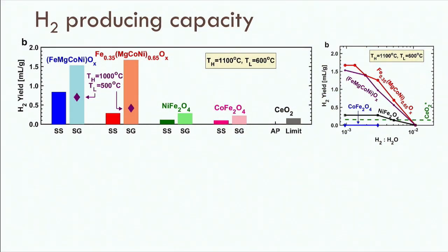In the interest of time, I'll keep it short. This is at 1100 degrees Celsius, and you find that the gray bar out there for cerium oxide is the thermodynamic limit for cerium oxide. And you find also cobalt ferrites in two different ways of synthesizing this material. One is a sol gel technique, which seems to be working better. The other is solid state sintering method. And you have nickel ferrite and cobalt ferrite. That's the performance of the existing materials.